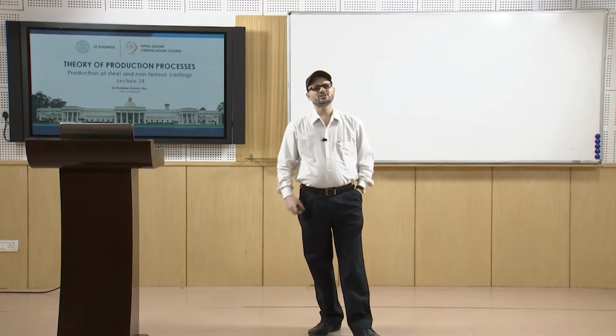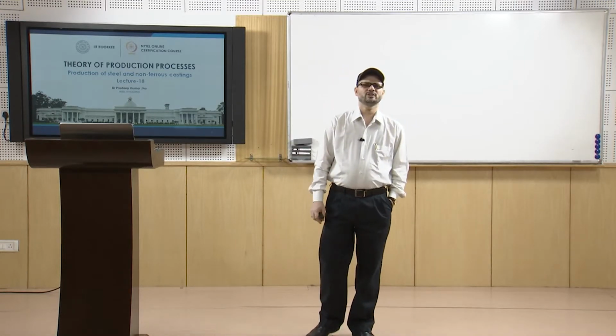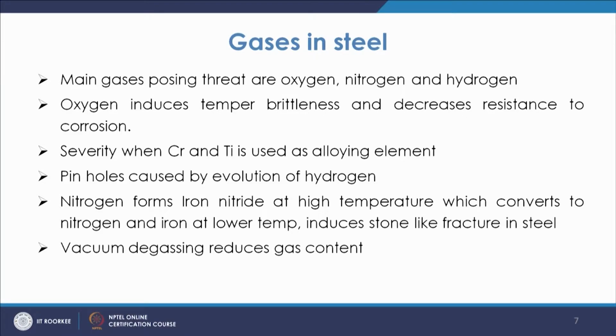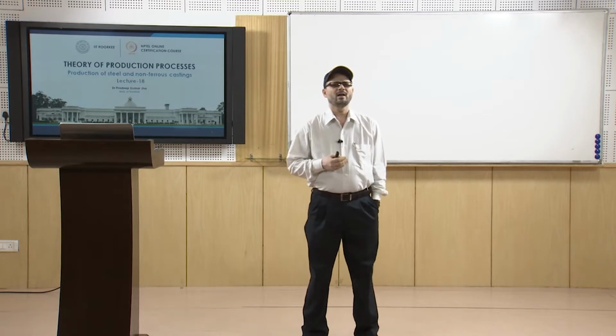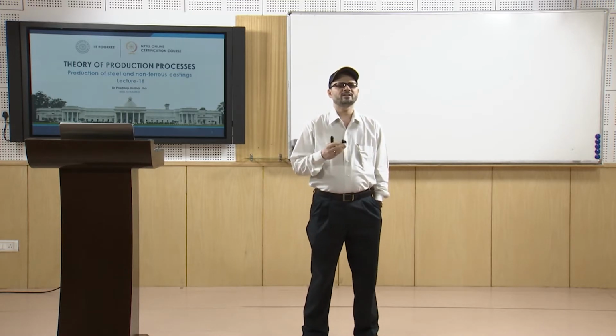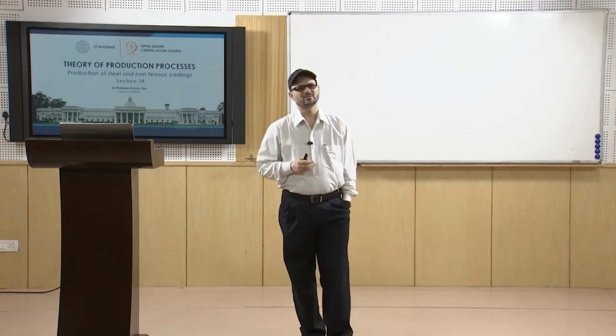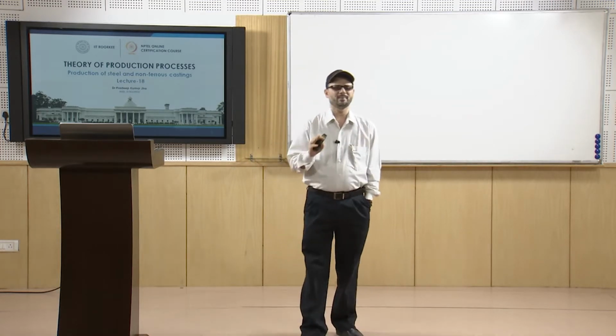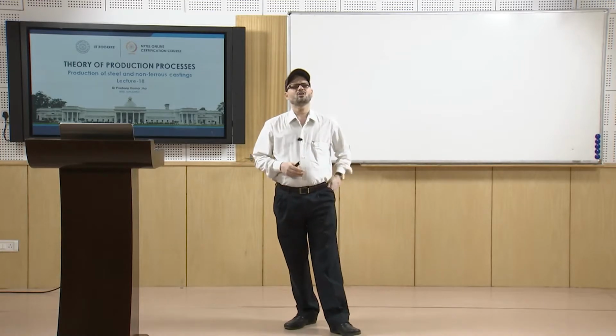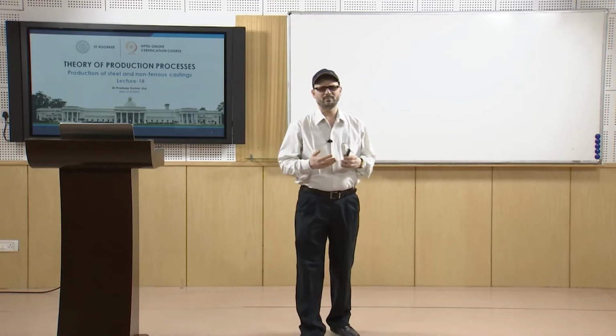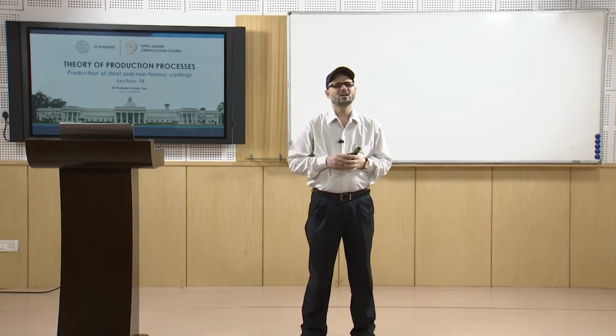The gases which normally pose a threat in steel making are oxygen, nitrogen and hydrogen. Oxygen basically induces temper brittleness and decreases resistance to corrosion, and it is severe when chromium and titanium are used as the alloying element. So, basically that is why we go for the deoxidization of the melt, so that the oxygen is removed.